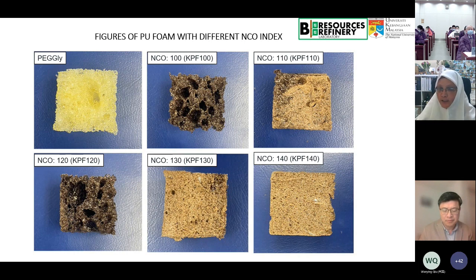And what we did is we make a hydrogel from that. You have the solvent and then you cross-link and you have a hydrogel. We did it for growing materials, and it is very good as far as germination is concerned. So we embedded the cellulose hydrogel inside the PU. That's why I said 100 is the best, because it absorbs so much water, so it retains water, and biodegradability is very good.